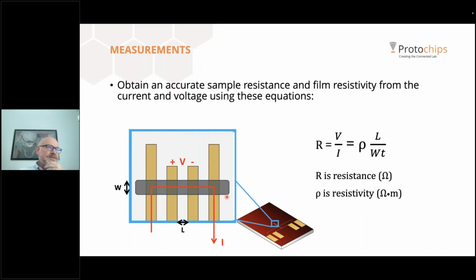But back to our thin film. So with a voltage and current measurement, we can calculate the resistance of the segment of material that's in the middle between the two inner electrodes. And if you know its geometry, which is easy to measure, its width, its length, and its thickness, then you can calculate its resistivity using the equation shown here. And this resistivity is a fundamental property of materials. It's not dependent on its geometry, but it could be dependent on the deposition technique you used to create that material. For example, sputtered materials or impure materials can have a resistivity that's very different than a bulk value that you might find in a book. And now that the geometry is easily characterized, you can measure its width and length in the TEM and get a true accurate measurement for that material deposited using that technique. You can measure the thickness in a number of ways. Profilometer, there's ways to measure in a TEM.